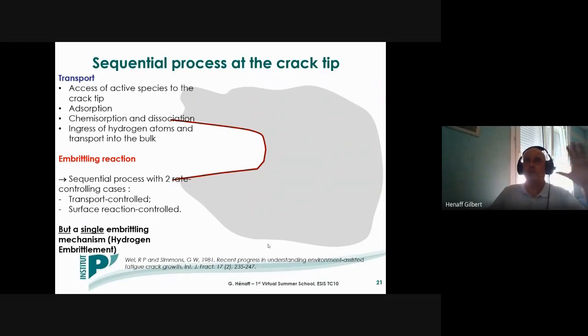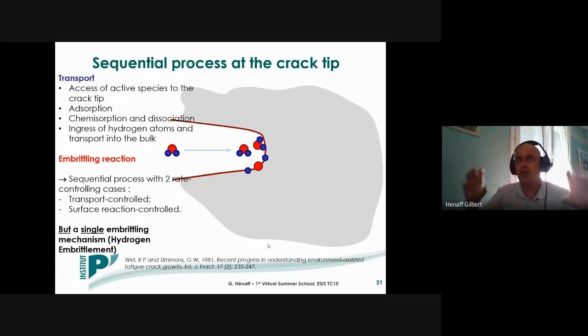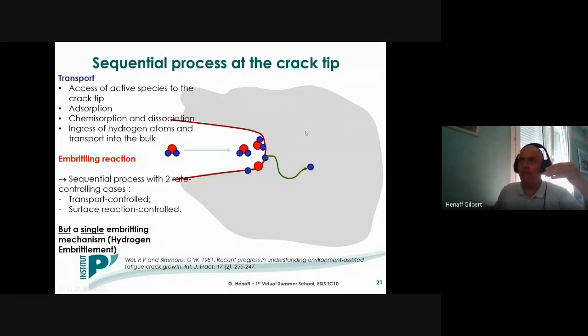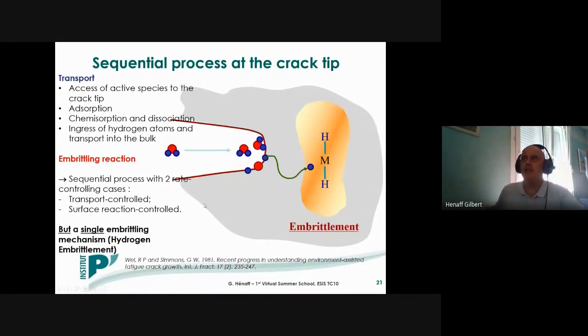So first, you have the transport, consisting in the access of the active species towards the crack tip. Then you will have the physical adsorption of these molecules, for instance, water vapor molecules, on fresh surfaces formed at the crack tip, and then a chemisorption process leading to the dissociation of the water vapor molecules, and in particular with the formation of hydrogen atoms. And some of these atoms can then ingress into the material and can diffuse within the cyclically deformed region at the crack tip, where the embrittling reaction takes place.